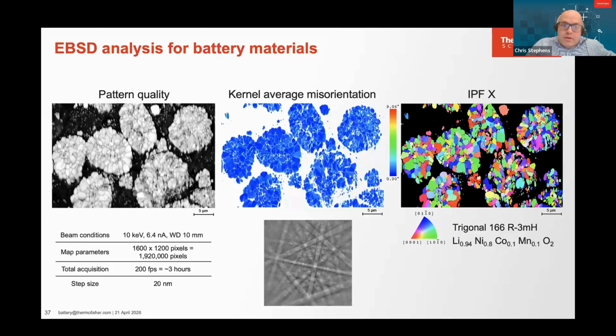The kernel average misorientation is very helpful because this enables you to see how the localized stress will accumulate. And on the right, you can see the orientations of every single one of those secondary particles. And the diffraction pattern you see in the middle is what you're getting from this. And because these are trigonal, you kind of need nice patterns to be able to do these. And this is what you're able to now achieve with a modern EBSD system.